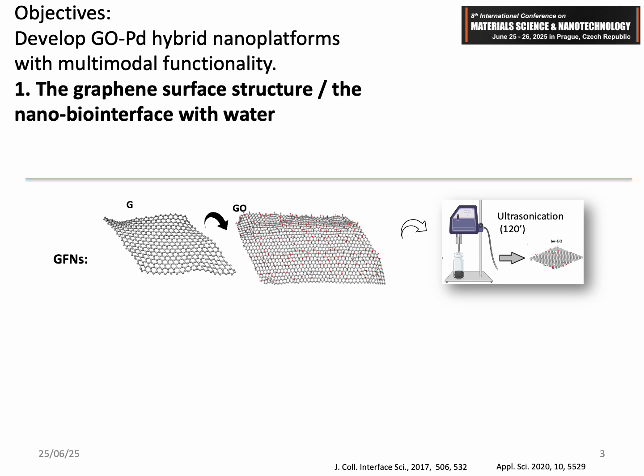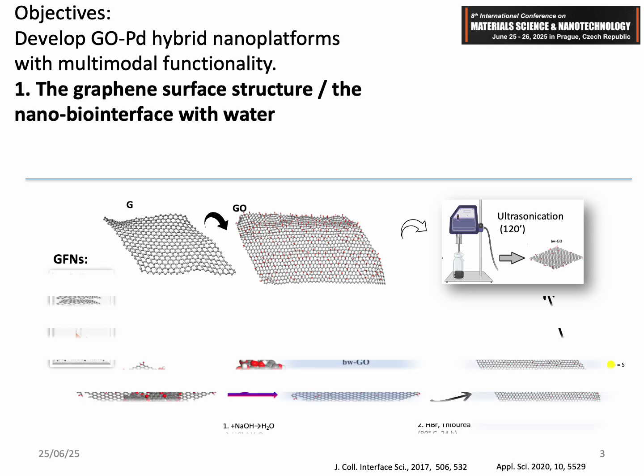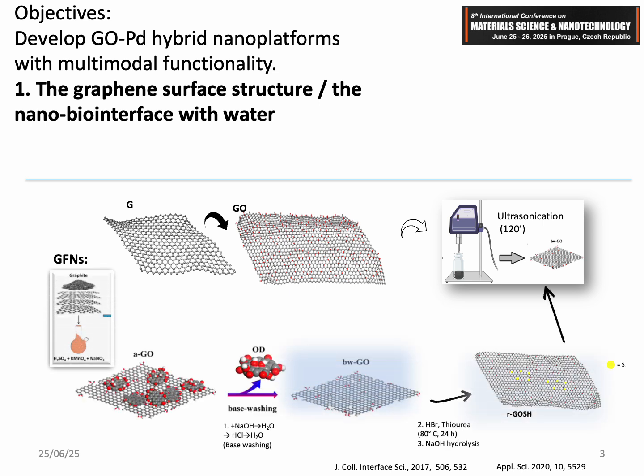So to control the surface termination and the defect density of the graphene nanomaterials, as well as to achieve a narrow lateral size distribution of around 200 nanometers in our nanosheets, we perform a mechanical exfoliation using 2-hour ultrasonication. Also, it has to be noted that the graphene oxide is synthesized via the Hummers method, which yields functionalized graphene sheets, often coated with tightly bound oxidative debris.